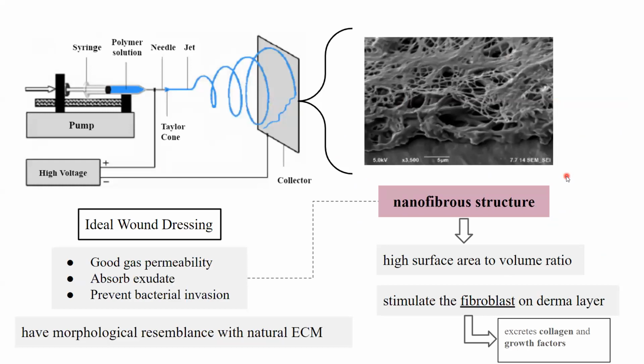In this study, the electrospinning technique was used, and this technique is preferred frequently for producing wound dressing materials. By this technique, we can get a porous structure similar to the one we can see in this picture. Since electrospun nanofiber mats have a high surface area to volume ratio and microporous structure, wound healing is started quickly by stimulating the fibroblasts of the dermal layer. Fibroblasts, as I mentioned before, excrete collagen and growth factors for repairing the wound.